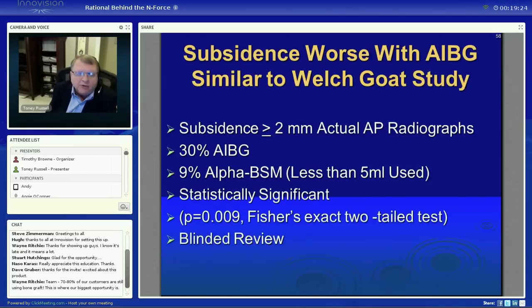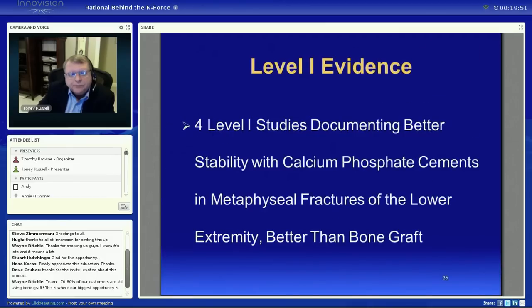What we found in the study is that 30% of the bone graft group, you can actually tell within 3 to 6 months that the reduction collapsed. So that's a 30% failure rate. 9% of the alpha BSM group collapsed, but these are cases where there was less than 5 cc's of material used. So this kind of got us thinking that just like implants, you got to have the right number of screws and a big enough plate.